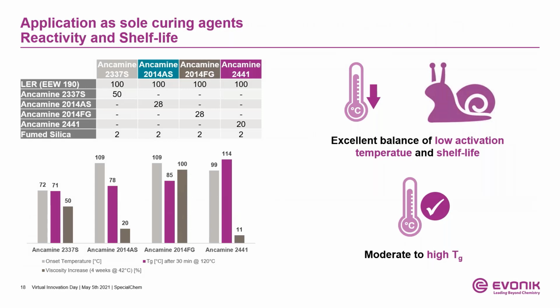When considering the modified aliphatic amines as sole curing agents, let's start with a look at the curing onset, the thermal stability after the recommended curing schedule, in this case 30 minutes at 120 centigrade, and the shelf life in terms of viscosity increase after storage at 42 centigrade for 4 weeks. All tests are based on simple model formulations consisting of a standard epoxy resin, the respective hardener, and some thixotropic filler, as can be seen in the table on the upper left-hand side.